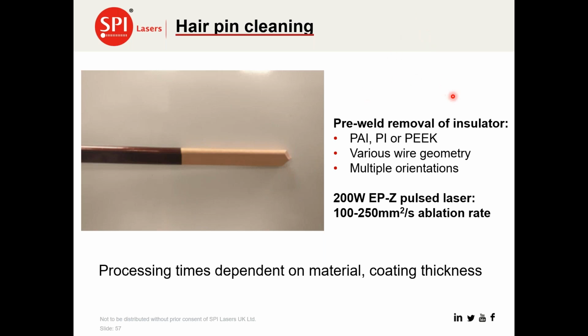We find that our 200-watt EPZ and EPM lasers are very good lasers for this kind of application, and can get high removal rates, and are actually currently being used in industrial installations in certain geographies. The processing times are very dependent on the materials and the coating thicknesses, so it's difficult to generalize on processing data.